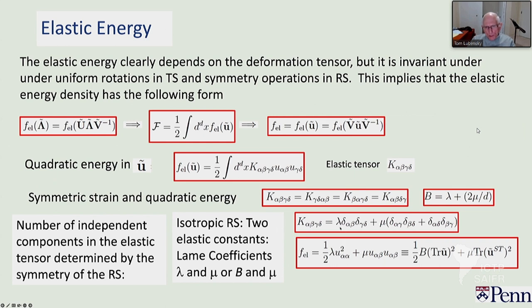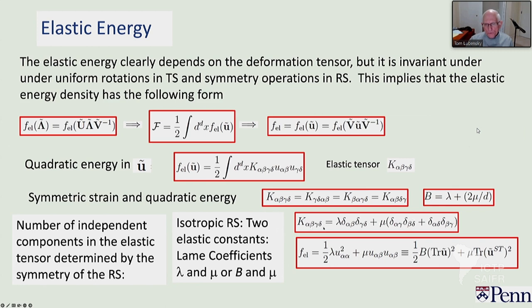For an isotropic system, the only tensors at your disposal to construct an elastic tensor are delta functions. So you can write it in terms of the two Lamé coefficients, lambda and mu: K_alpha_beta_gamma_delta equals lambda delta_alpha_beta delta_gamma_delta plus mu times the symmetrized version. The elastic energy then depends upon the trace — which is the change in volume — plus the symmetric traceless tensor part, which is all shear. So mu is the shear modulus and B, which equals lambda plus two mu over D, is the bulk modulus. In two dimensions, B equals lambda plus mu, and B goes to zero when lambda equals minus mu.